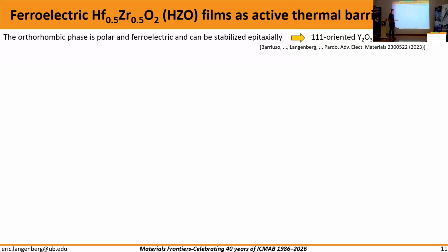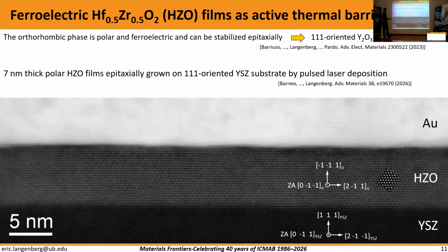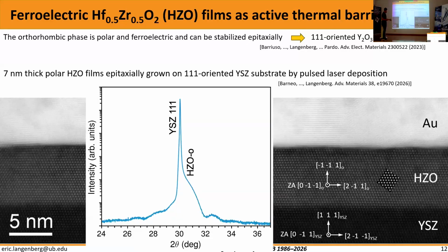And then we can actually stabilize this ferroelectric phase epitaxially, and we did that using a 111-oriented YSZ substrate, and then we can stabilize the polar phase. We proved it a few years ago. And that is why we use this material as a flagship to check how the domain walls can change the thermal conductivity. And then we grow the sample on YSZ. So it was epitaxial and polar. We have the orthorhombic polar phase. Okay, and that was our test sample.